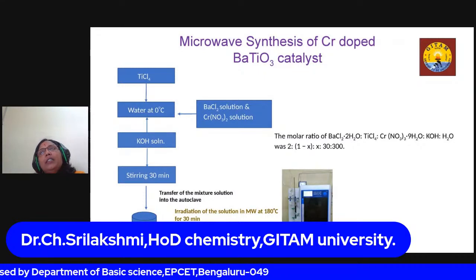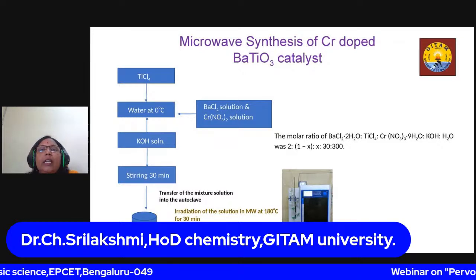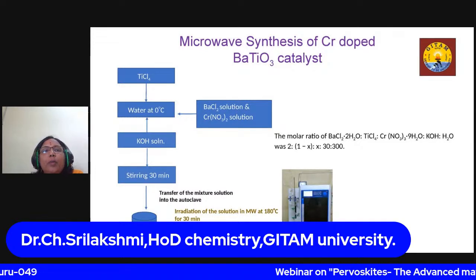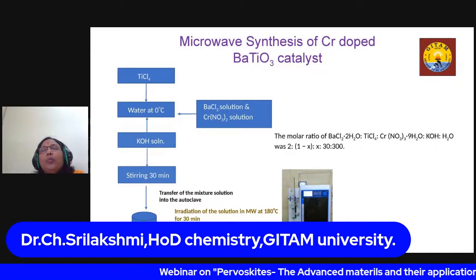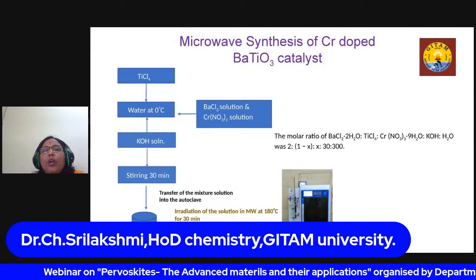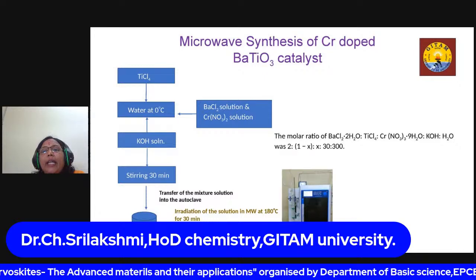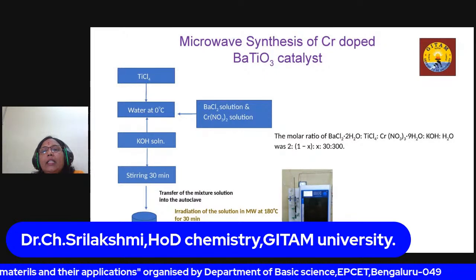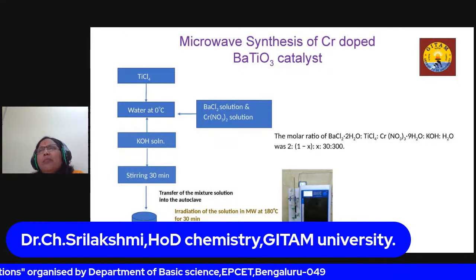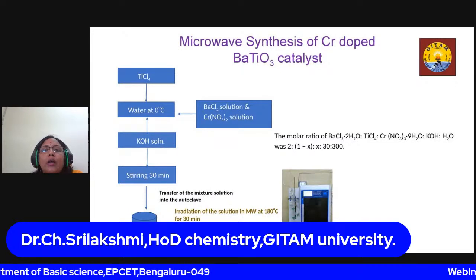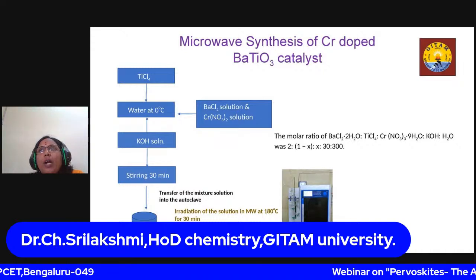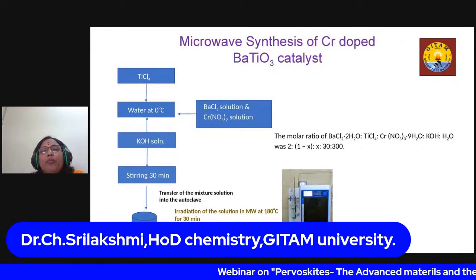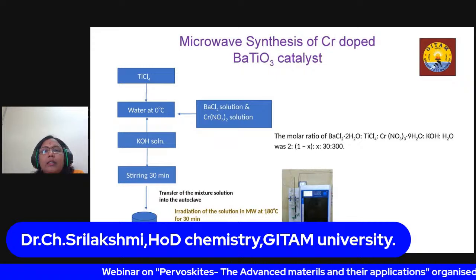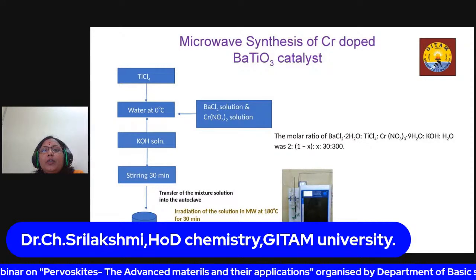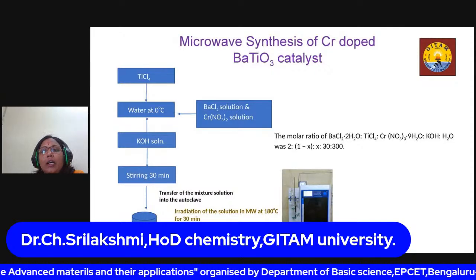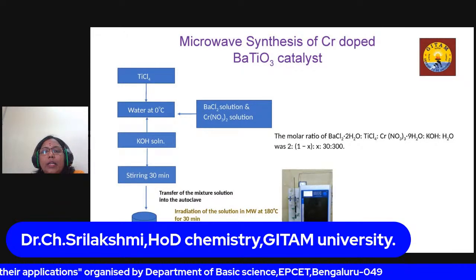To optimize these conditions took me 3 months. You may think this is silly, but why did it take so long? Because of this kind of molar ratio. If I take less water or vary this by 10 or 15, the phase does not come. Something else comes, different types of compounds. And even 1 degree matters in microwave. So finally, 180 degrees for 30 minutes is the optimized microwave reaction condition to synthesize a pure form of the perovskite.